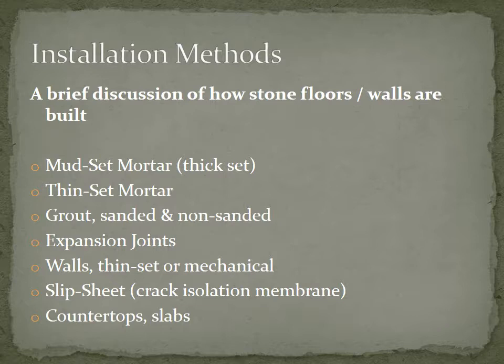When you see the sanded grout and you have to resurface the floor to flatten it, there could be problems, because a lot of that sand, silica sand from the grout, could come out and get stuck under your abrasives and just give you a real hard time as you're trying to polish. So watch out for that. I have had jobs where they wanted to sand the floor and they used sanded grout. They wanted to do a lippage job of flattening, and I had to have them remove the grout and put in non-sanded grout. So that's the right way.